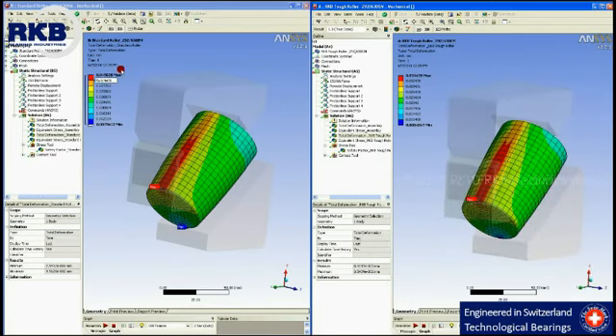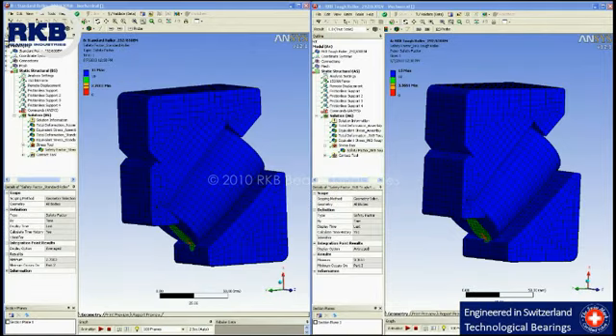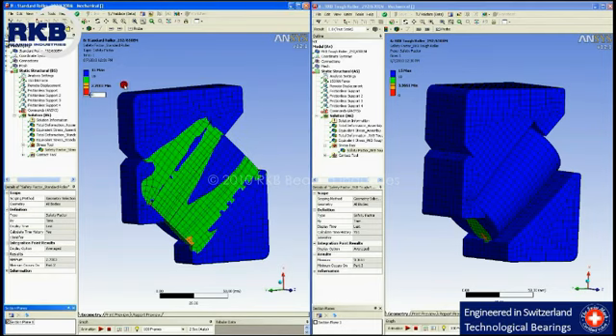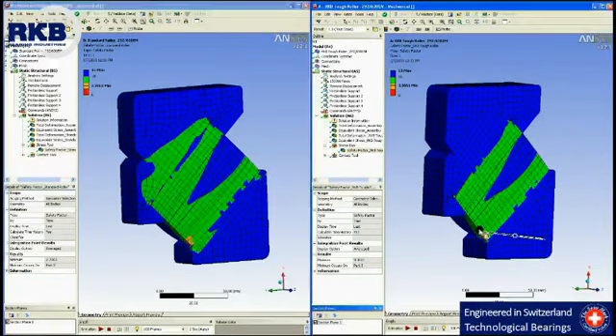respectively 0.045 mm and 0.035 mm. Finally, always owing to lower mechanical properties, the standard roller has a safety factor of 2.7. That is lower than that of the RKB Tough Roller, which is 3.3. This means an improvement of almost 20% of the safety factor.